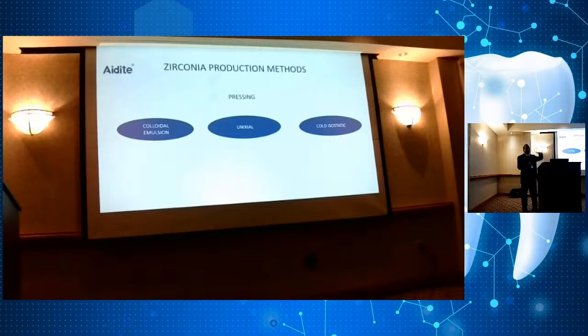Uniaxial pressing is basically taking some material and compressing it from 2 different sides. Okay, so uniaxial pressing is relatively inexpensive. You're applying 20 tons of pressure to it, and it forms a disc. At that point, you're curing it in the ovens, the large capacity ovens. You're burning out the trace elements like the binder, and then it's ready for use. So I really do advocate the cold isostatic pressing.